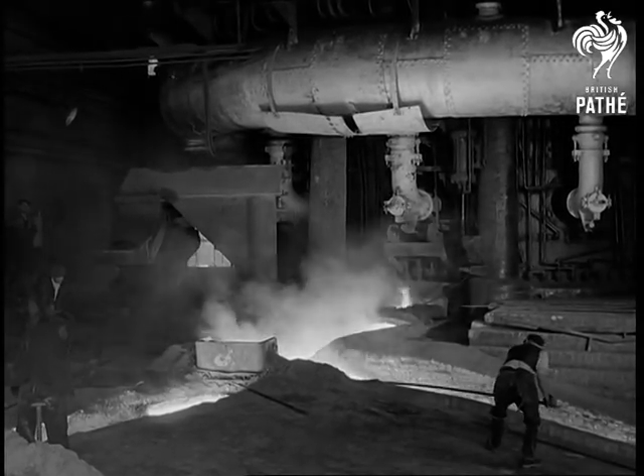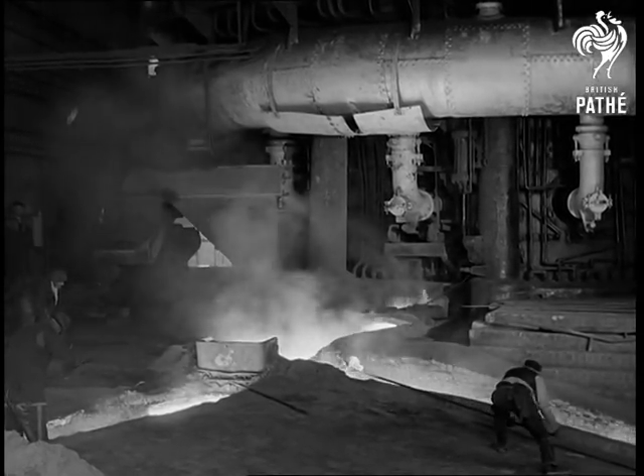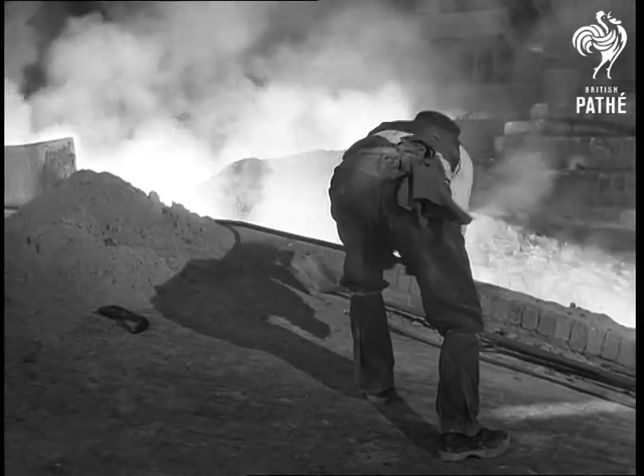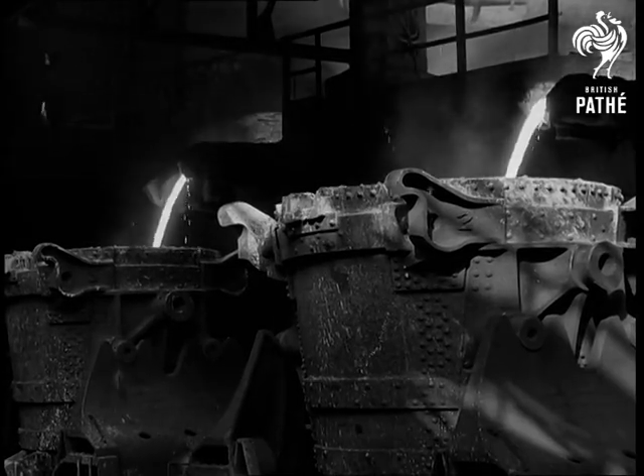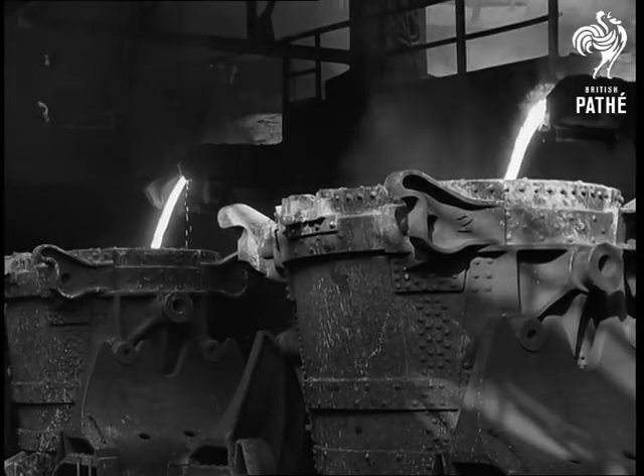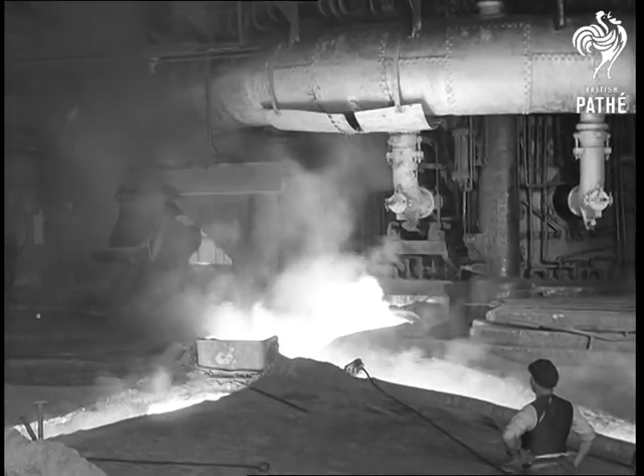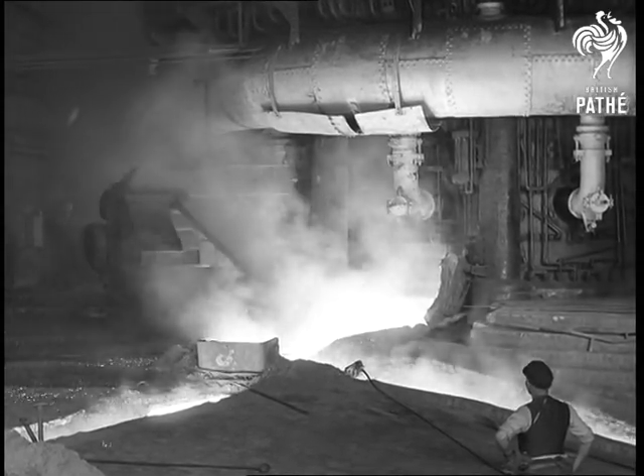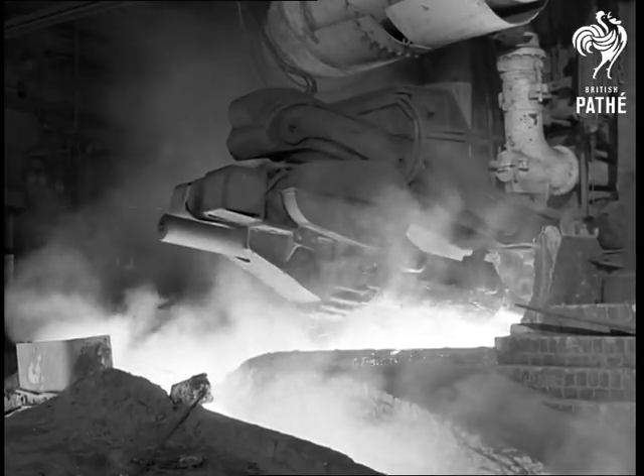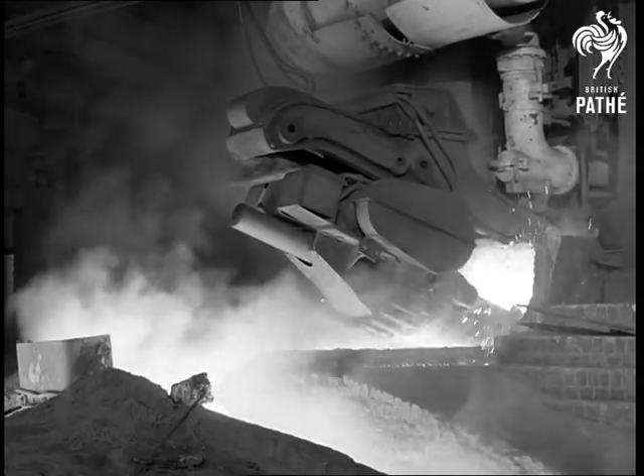From the trough, the molten iron flows into cast iron channels, again lined with fire clay a few inches thick and with a thin covering layer of sand. These channels lead the molten iron into ladles much heavier than the slag ladles and lined with fire bricks. These also run on lines at ground level. The tapping is now finished. A special gun moves into position to force fire clay into the tap hole, thus sealing the furnace again. Smelting continues.